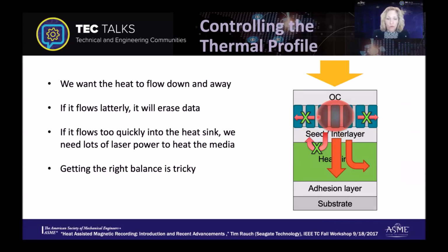We also do not want good lateral conduction. We do not want it to conduct laterally because that will actually spread the spot or erase other data that we might have on the disk. We also want it to come down and away, but we do not want this heat sink, when it becomes hot, to conduct the heat back up into the recording layer, because that will also erase data. And so this is a challenge directionally, with anisotropic properties, and really is a difficult and challenging balance, using nanoscale heat transfer effects to be able to control a lot of those properties.